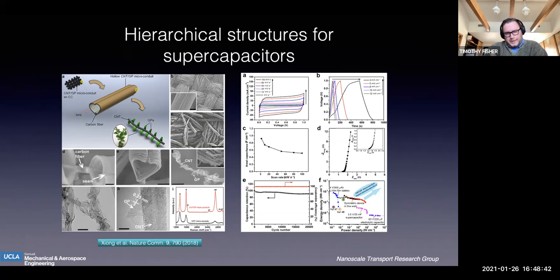So what we did is we just had to tweak our recipe. Once we had grown the carbon nanotubes, we changed the processing conditions in the same chamber, and we grew petals off of the carbon nanotubes. After that, they stayed together, right? They didn't collapse because of the interference between the graphitic petals. It kept the mechanical structure. So again, you don't have to read all the charts, but the theme is that some fairly simple, intuitive mechanical concepts can work at this scale, and completely transform the performance and behavior.